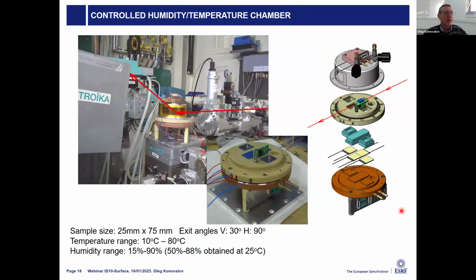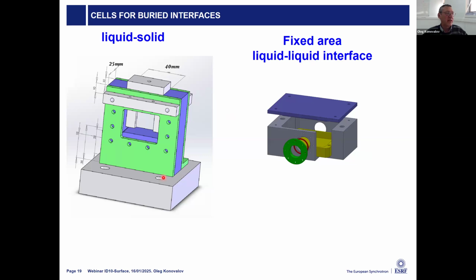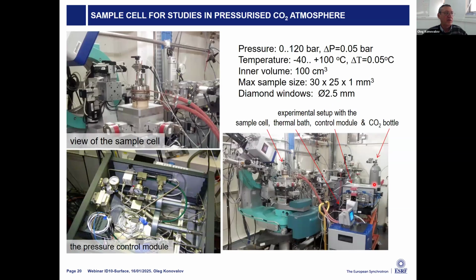We also have a humidity cell, if people want to study how the films behave at different humidity. Then we have some cells for solid-liquid interfaces. This is an example of a liquid-liquid interface with a fixed area, so we cannot change it, but for many cases this is enough. Then we also have a special cell to study in a CO2 environment, to go from the gas to liquid and the supercritical state at different pressures up to 120 bars and also temperatures up to 100 degrees.